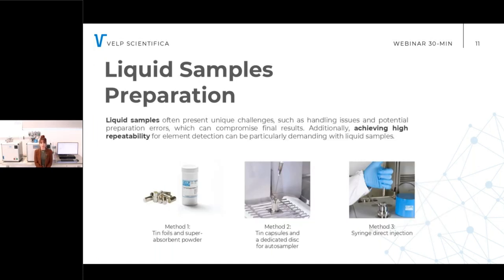While for liquid sample preparation, we have 3 different methods because several difficult challenges can be presented. The first method employs the VELP super absorbent powder to soak up the liquid and solidify the sample for easy encapsulation within a tin foil. The second method, for laboratories handling larger volumes of liquid sample, is that VELP can offer thin capsules with a dedicated disc for capsules. The third method is for analysis requiring high sensitivity compared to the previous methods. So there is a direct injection into the combustion area directly with a syringe. If you require high accuracy and precision, this is the method of your choice.